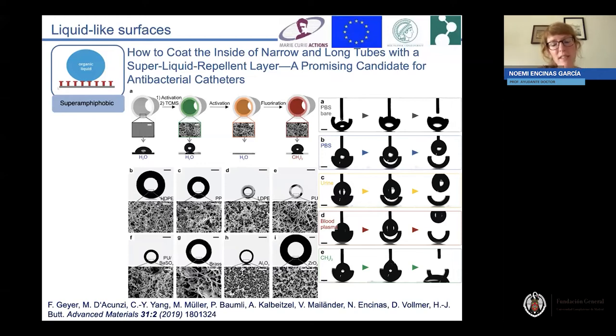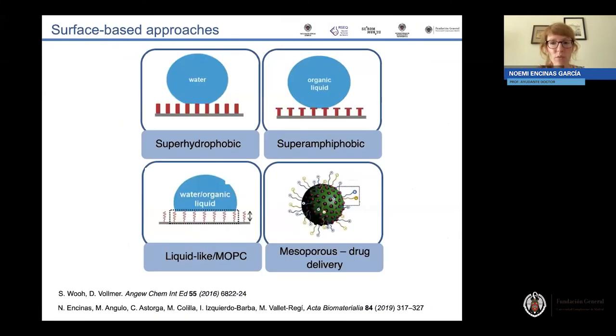And we coated these types of tubes with silicon nanofilaments. After subjecting them to different types of solutions, such as a buffer solution like PBS, a urine solution, blood plasma, or even a low surface tension solution, such as methylene iodide, we saw that in every case they were able to repel the liquid, and therefore we could envision a very nice medical application for this type of super amphiphobic surfaces.